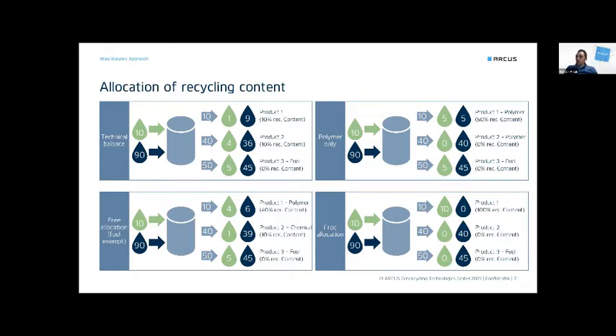The other extreme is the free allocation, where you have 10 of 100 pyrolysis oil, and you assign the 10 to one polymer monomer. So you might have 100% of recycling content. This excludes the real yield distribution, and therefore this is not to be considered a way to go, because of course you don't produce 100% of monomers out of pyrolysis oil. And therefore there are two interesting options. The first is polymer only: you assign everything out of pyrolysis oil which goes into polymers or chemicals to one single polymer. You might achieve up to, in this example, 50% of recycling content, and the rest is gone, so to say.